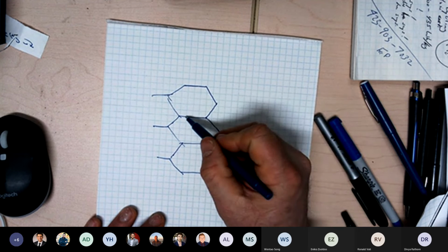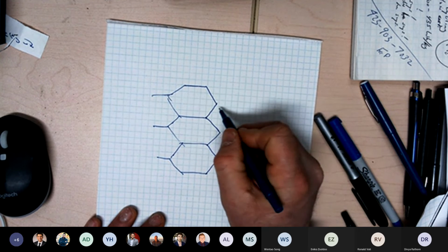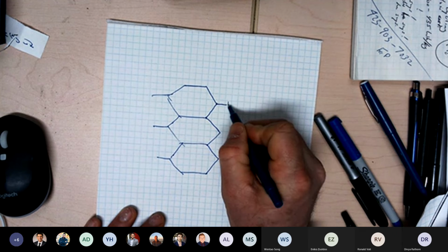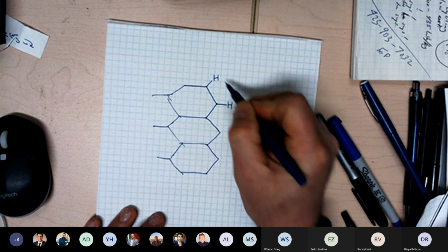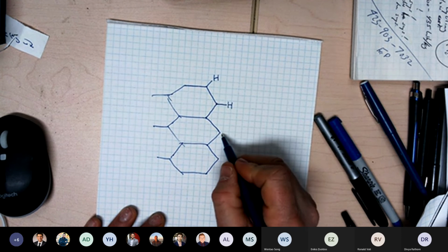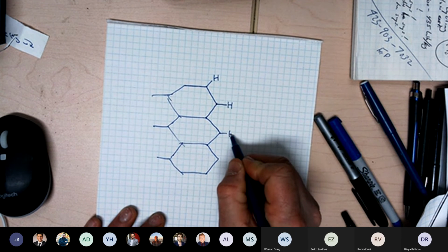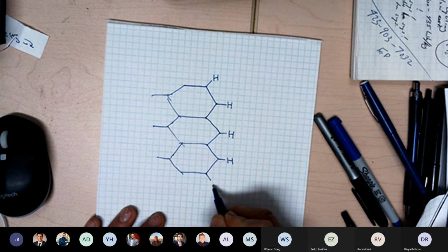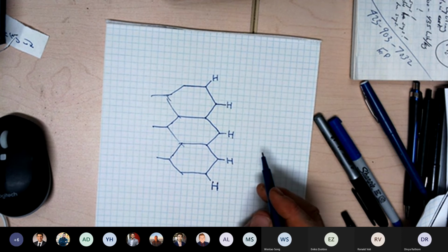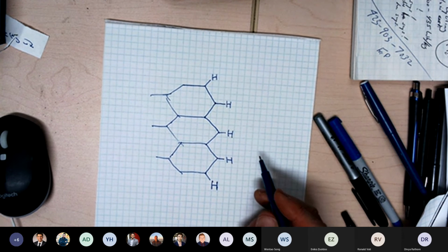So there's double bonds and single bonds in here. But the edge is thought to be, especially if you heat them in inert gas, the only thing that can be terminating at the edge predominantly is hydrogen. Hydrogen terminated carbon. That's why the hydrogen to carbon ratio is so big.